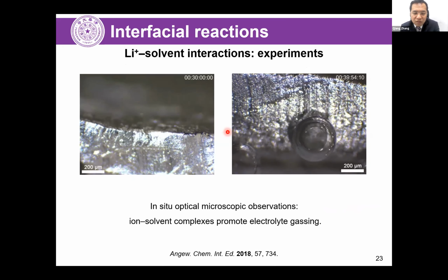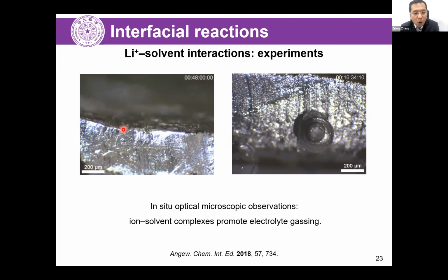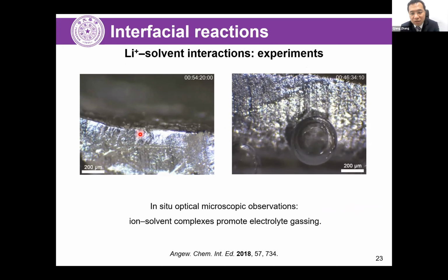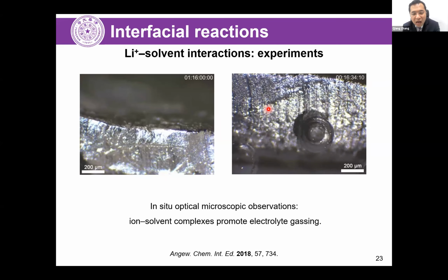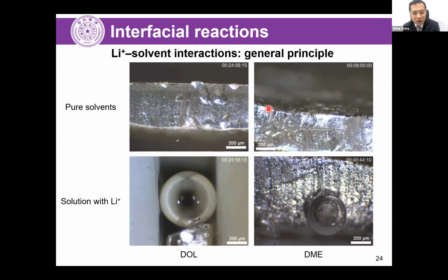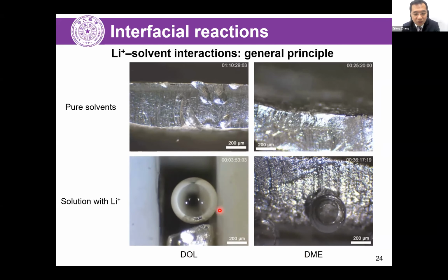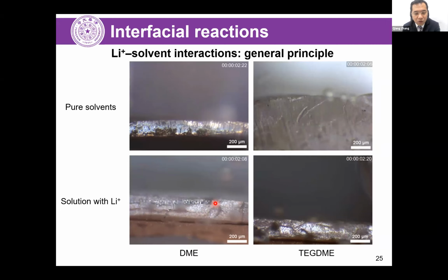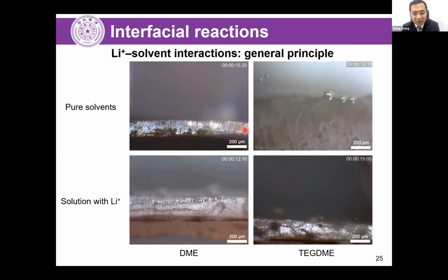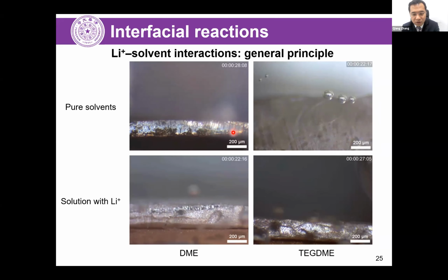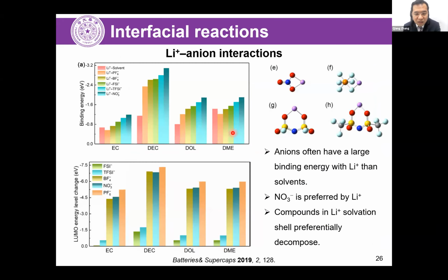In fact, if we try to dip the lithium metal anode into pure organic solvents, there is quite little gas evolution. While in the salt-containing electrolytes, the gas bubble formation was quite quick. And such a phenomenon was a universal one, because in pure solvents, whether in DOL or DME systems, the gas evolution was quite slow. And we also try to compare with other electrolytes, and the results were quite similar. We found the ion-solvent complex structure was quite important for the decomposition.